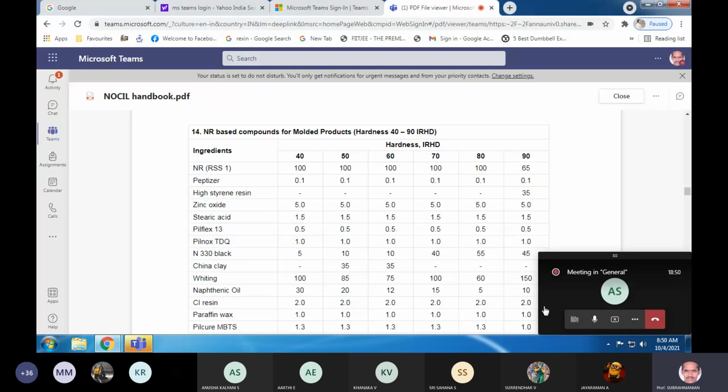There are amine treated, silane treated. So that is one variety in the non-black filler, non-reinforcing. If you use silica, then it becomes reinforcing. With silica in hydrocarbon rubber, even today we use a coupling agent. Chemical coupling agents are necessary. In case of China clay, we don't look at any such reinforcement.